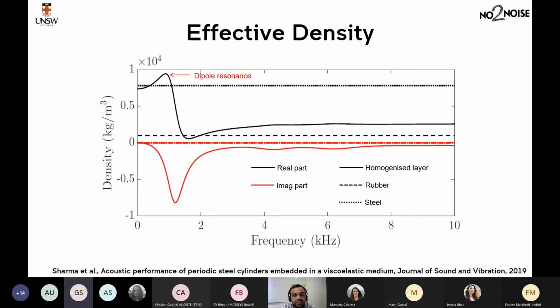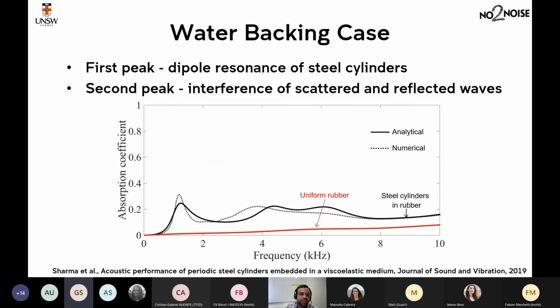If you pick a particular combination of material and geometric properties. So this is how the absorption coefficient looks when you have water on both sides and hard inclusions in your rubber medium. It's just one layer. So you see that even when you have hard inclusions, it is performing better compared to a uniform rubber. The absorption coefficient is not as high as it was for voided inclusions. For voided inclusions, it was about 100% sound absorption. But here, even though it is 20%,